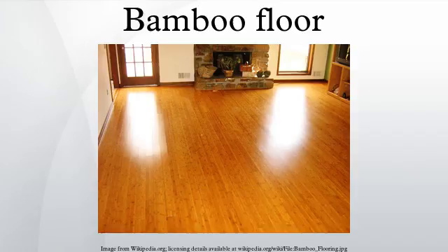The bamboo flooring is typically made by slicing mature bamboo poles or culms into strips. These culms are cross-cut to length and then sliced into strips depending on the width desired. The outer skin and nodes are removed. To remove starch and sugars, the strips of bamboo are boiled in a solution of boric acid or lime. The bamboo is then dried and planed. Natural bamboo color is similar to beech wood.